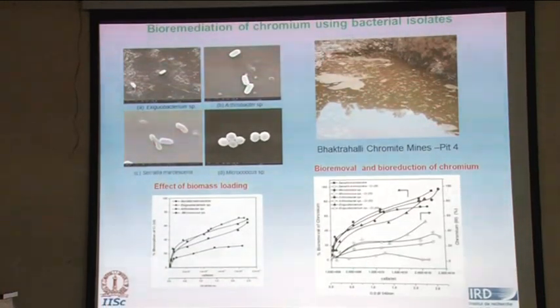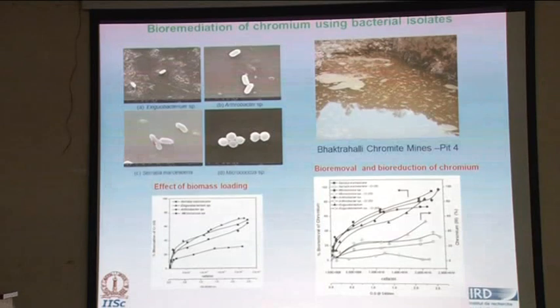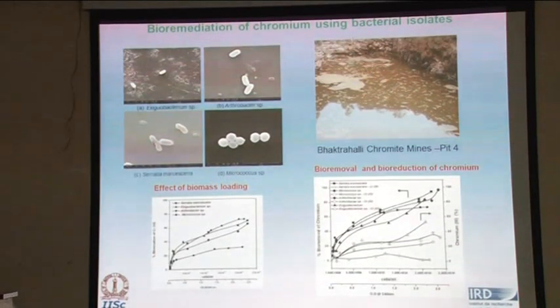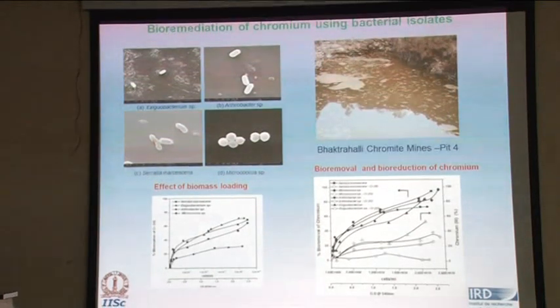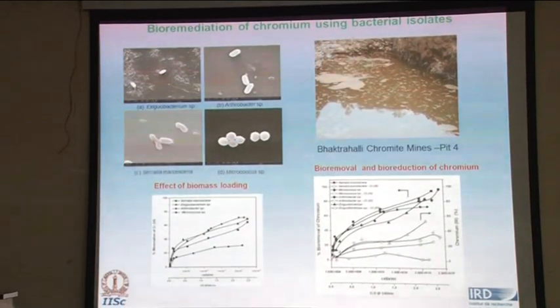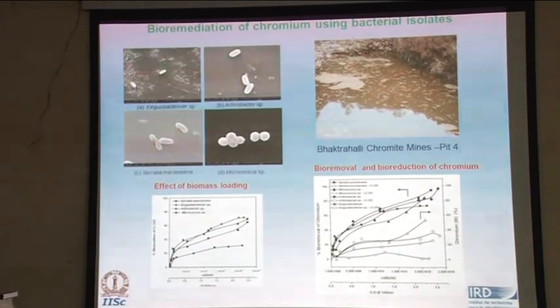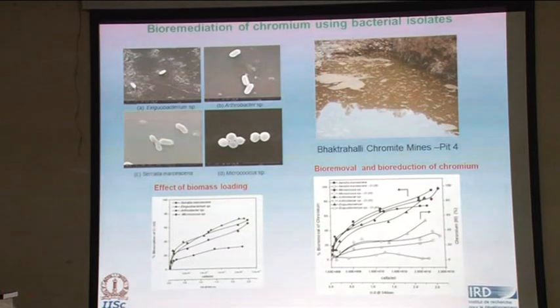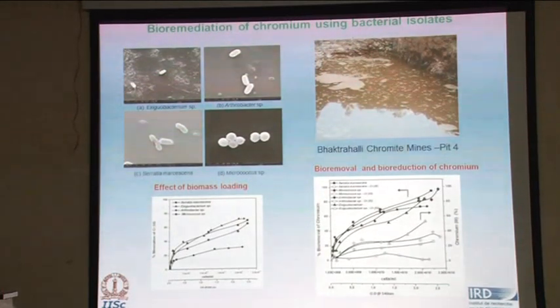In the context of the chromium remediation, there is a mine in the Hassan district which is called the Bhaktarhalli mines. So we actually isolated these organisms from this mine site. We collected the water samples and used standard microbiological protocols. And these are the organisms that we could identify from this mine site. You can see that again the bioabsorption of chromium is quite good here. We can go even up to about nearly 100% removal for a given type of microorganism. These are different natural microorganisms isolated from the mine.